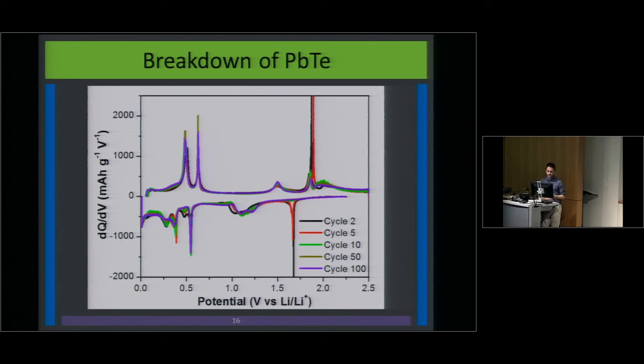So if we go back to that 100 cycles at a constant rate, we look at the differential capacity profiles. One thing I want to point out here is this red and black peak. It's been shown in the literature that once all the lithium is removed from the lead and from the tellurium, each lead and each tellurium atom recombine into that lead telluride crystal structure, and that's what this peak corresponds to. But you can see it's completely gone after about 5 cycles, so we're kind of wondering why that happens.